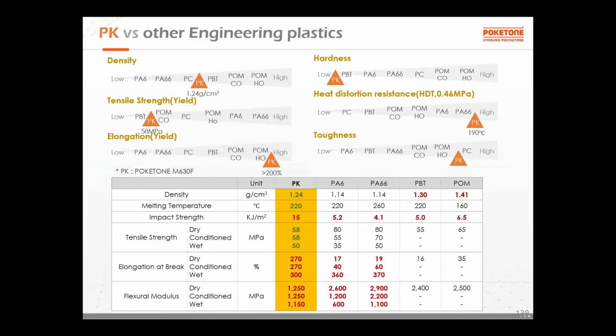So what is polyketone? First, polyketone density is 1.24, PBT 1.31, POM 1.41, and nylon 1.17. So its position is here. Tensile strength of polyketone is around 58 to 60 megapascal, so something softer than POM. Elongation at yield for polyketone is more than 200%, very high. Hardness looks soft, while heat deflection temperature is very similar to nylon 6, and toughness is similar to polycarbonate. Then polyketone is tough, high impact, and very competitive with engineering resins.